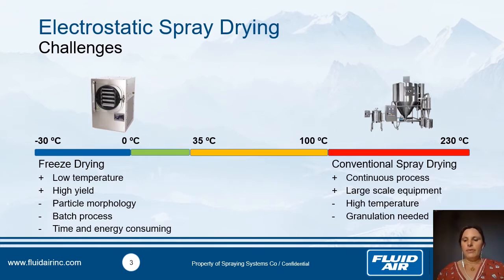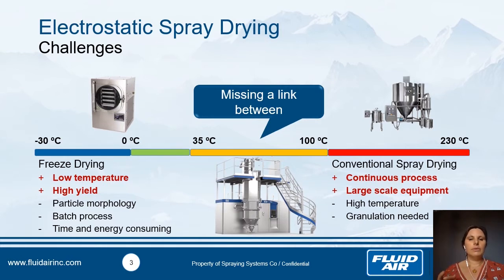So it seems that we have something missing in the middle. Something that works at lower temperatures than the conventional spray dryer, between 30 and 100 degrees C, with high preservation of thermosensitive compounds, working continuously, and easily scaled up from the laboratory to large scale. It's with this remark that we decided to develop the electrostatic spray dryer that I will present now.